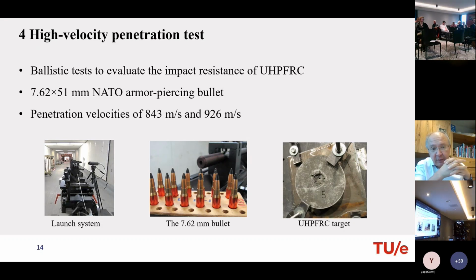We went there and they performed the test with our concrete, with this bullet, the 7.62 millimeter bullet. Later, they also did it with bigger bullets. I don't have that in this presentation. And later, they even tested in Germany with grenades, but that is classified information. And also with 2 penetration velocities. Here you can see already a sample that has been hit by such a bullet. Here you can also see with the high-speed camera how it impacts.